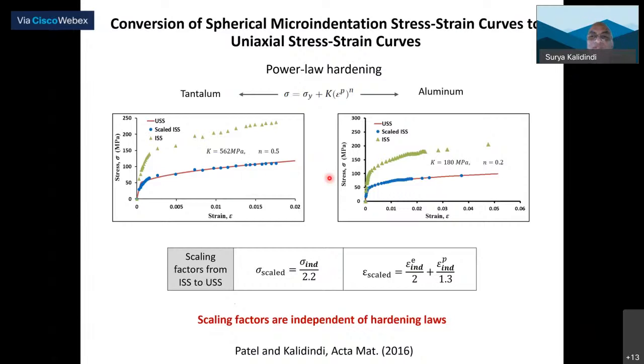So in both cases, the red curve is a uniaxial curve. The blue dots are from indentation, but scaled by these quantities. So once I scale this, then I can get a pretty good match. And it happens independent of hardening law. So the material can show all kinds of different behavior. Again, we have done a lot, all the way from very hard and high hardening rate materials to soft and low hardening materials.